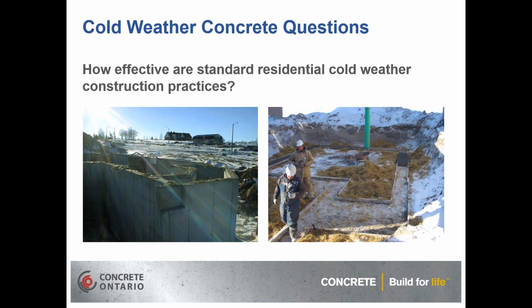This is a typical residential construction. We're looking at the photo on the left shows the foundation walls. And what we see here is during the cold weather conditions, when you strip the forms from vertical structures, given the high surface area that you have, the concrete will be exhibiting very rapid temperature loss. And if it wasn't protected sufficiently to reach the minimum 75% of the specified strength or the required strength for stripping the forms, then that concrete will take a long time to develop proper strength and durability.